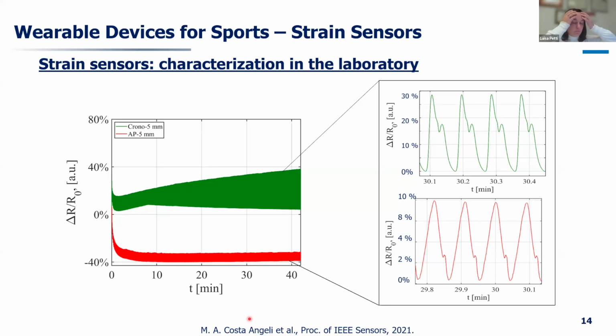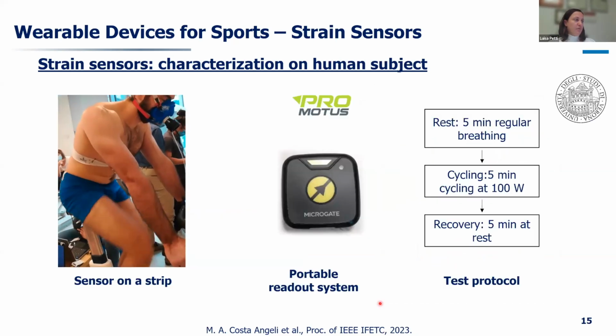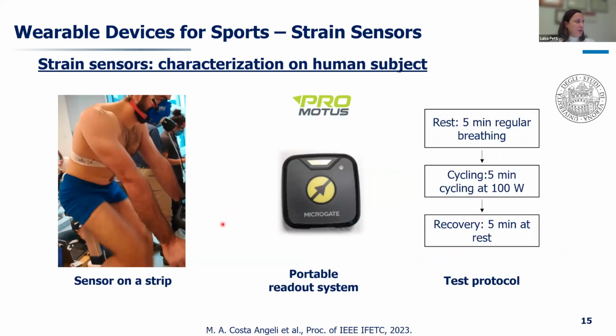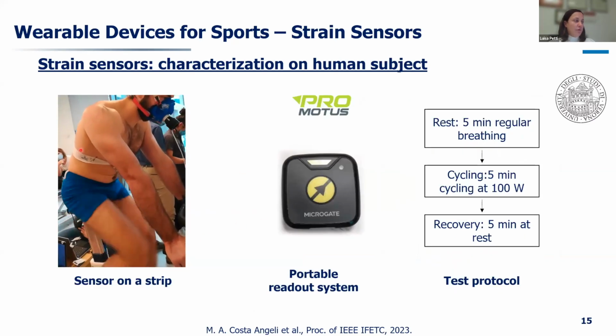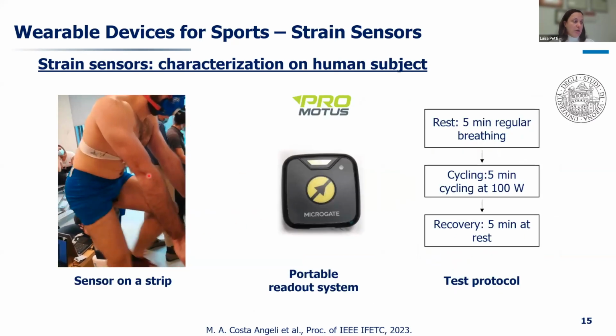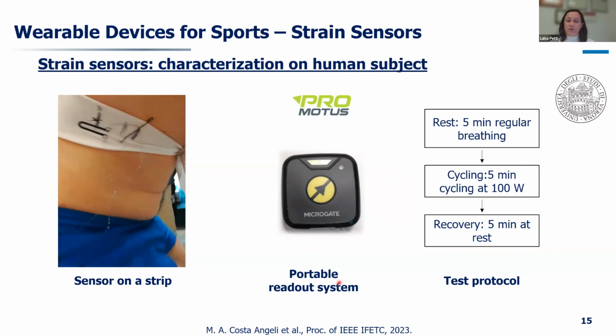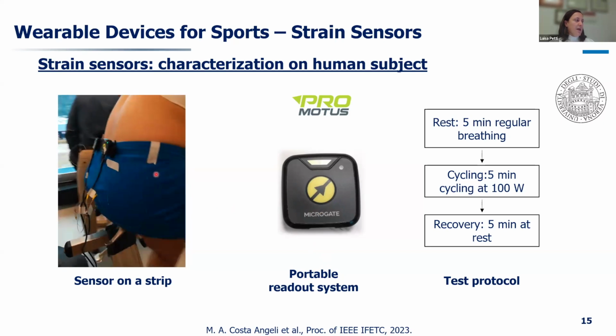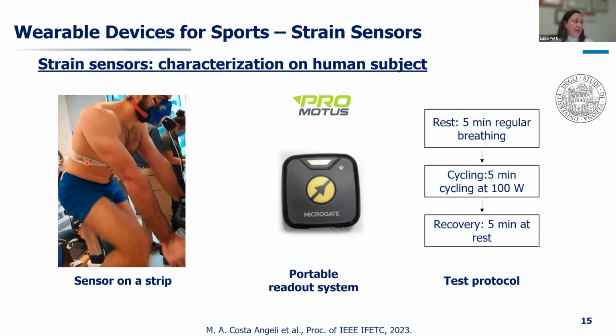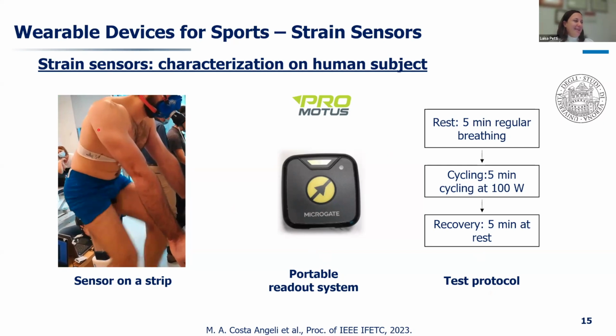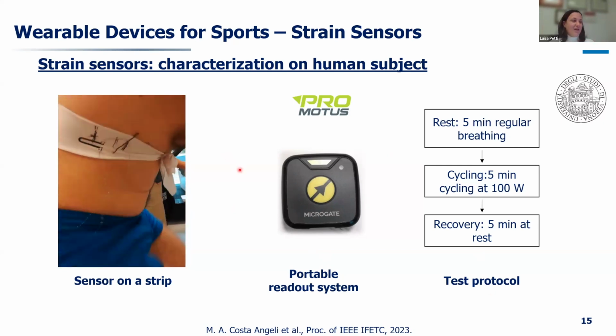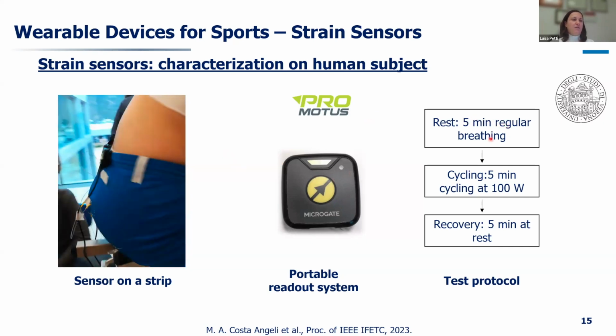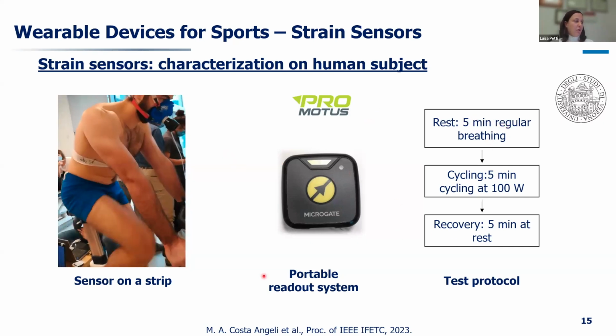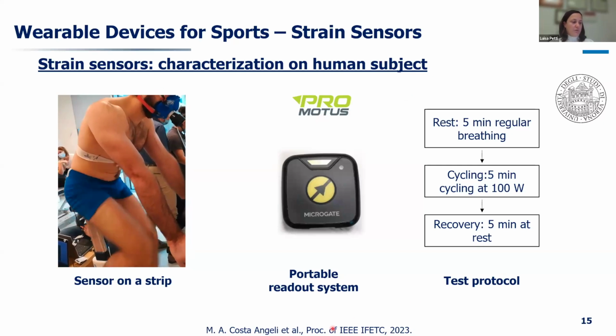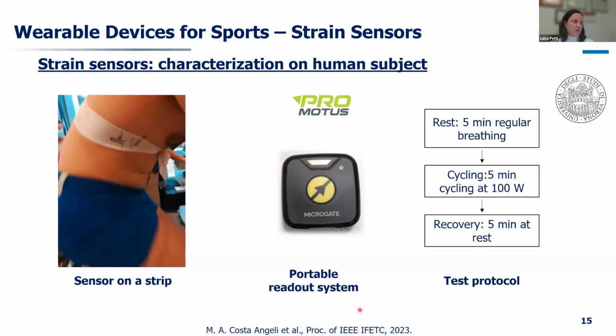So this is all highlighted in the proceedings of the IEEE Sensors in 2021. From that, we chose the best textile and moved into testing a sensor on a stripe, a very early prototype, connected to a portable readout system that was developed by the company, and testing this with a test protocol that was validated with the medical doctor, Silvia, that you see nearby here, of course against the gold standard of this very bulky and cumbersome mask. So 5 minutes of regular breathing, cycling 5 minutes, and then recovering. This is all tested at Promotus, as reported also in the IEEE FAC proceedings in 23.